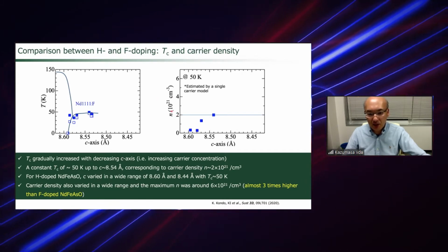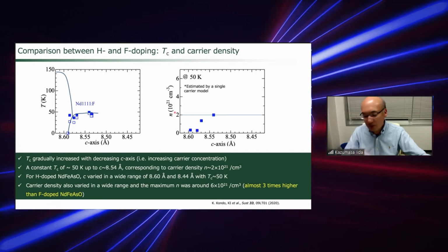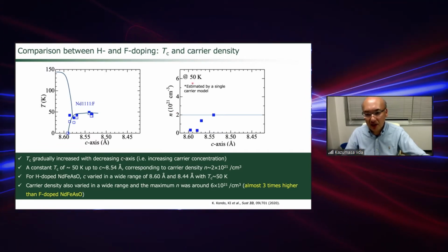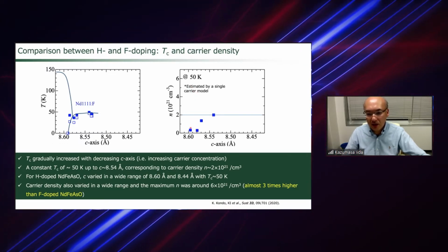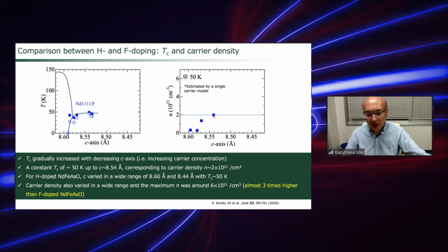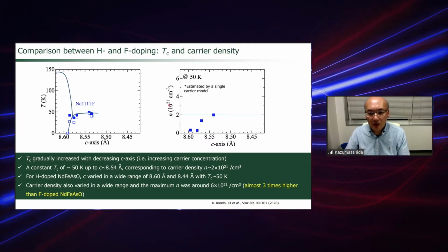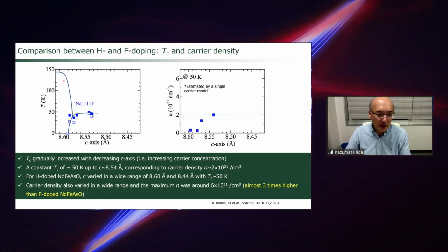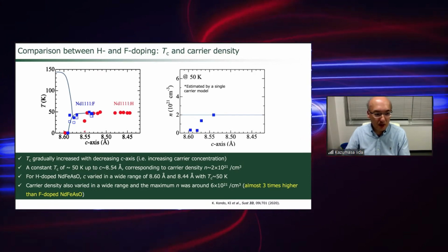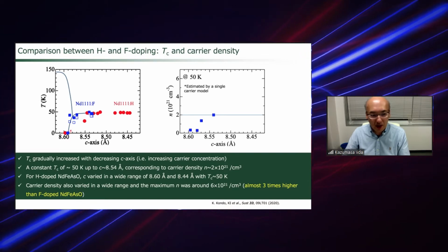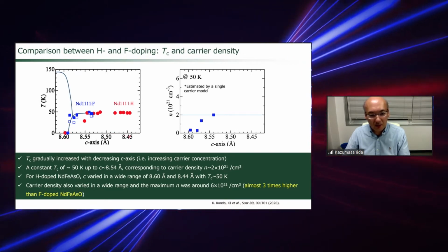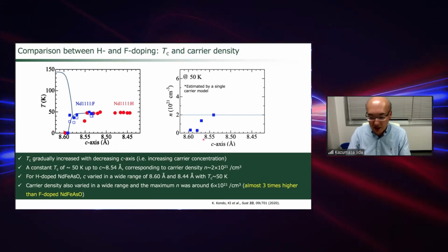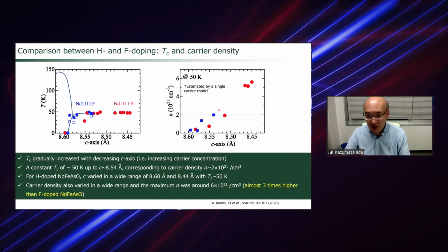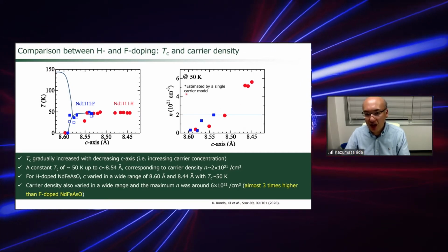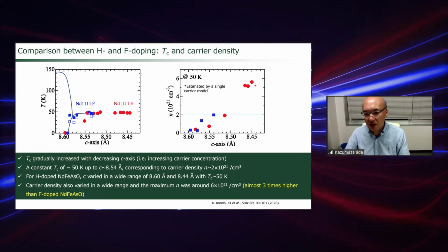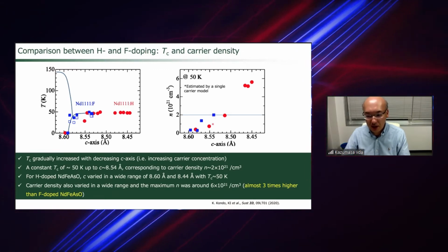At the same time, we measure the carrier density by the Hall method. The carrier density was estimated at 50 Kelvin by a single carrier model. As you see, the maximum carrier density reaches 2 times 10 to the power of 21 per cubic centimeter. And in this graph, we plot our hydrogen-doped sample. You can see that the C-axis lattice parameter varies over quite a wide range, down to 8.44 angstrom. At the same time, we measure the carrier density of these materials, and the maximum carrier density reaches 6 times 10 to the power of 21 per cubic centimeter, which is almost 3 times higher than the fluorine-doped sample.